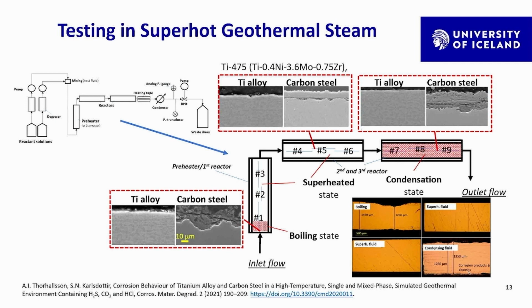Andre set up a series of connected reactors where we actually simulate the discharge, where we have basically wet steam, boiling condition, like we have downhole in the well. We have a superheated state here in the reactor in the middle, and then we have condensation to look at the different stages of the lifetime of these deep superhot wells.